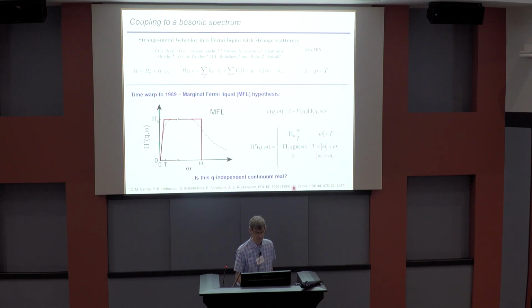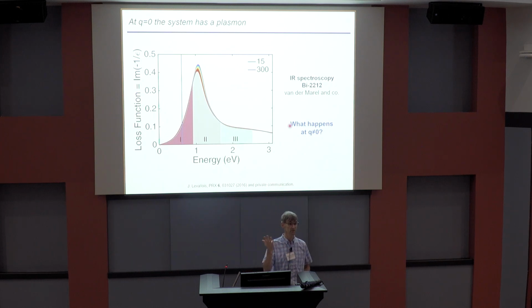Okay, so you can get some early hints simply by looking at the optical data. This thing I've called pi here is the polarizability. That's related to the dielectric constant. It's 1 minus v pi. You can measure that at q equals 0 with optics. And when you do, and by you I mean Dirk van der Marel and Tom Timusk and many other people, what you see is a plasmon. Depends on how you plot it, but if you plot minus the imaginary part of 1 over epsilon, then there's a peak. It sits at a plasma frequency of about an eV, and it's got some strange line shapes. It doesn't shift with doping the way you would expect, but there is a collective mode there. That's what you would get in a Fermi liquid too. But the question really concerns what happens in this system at non-zero momentum. So is there something frequency independent present or not?